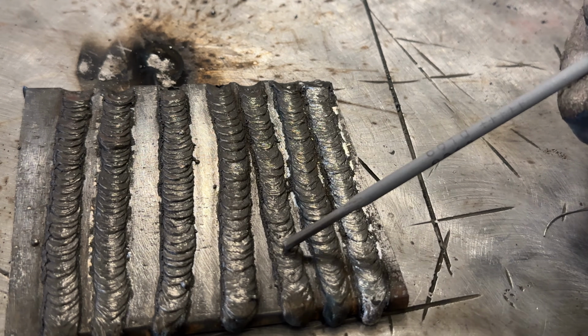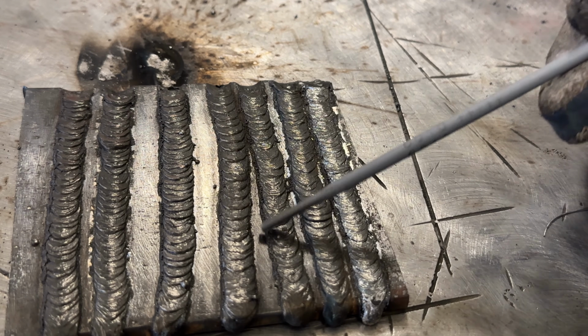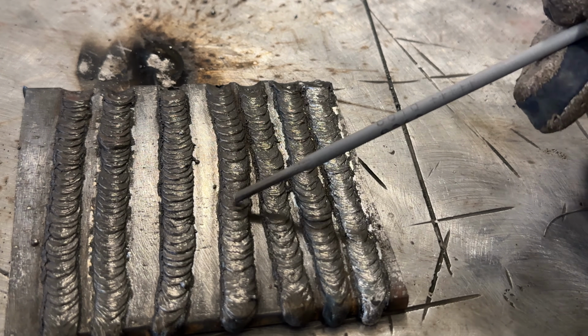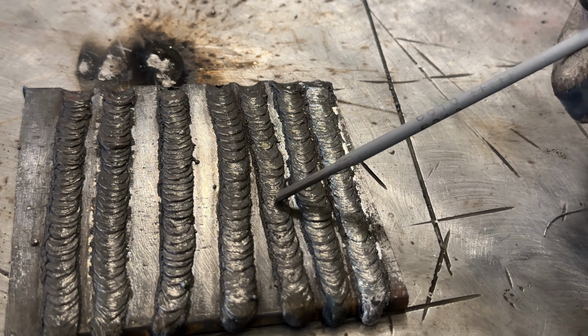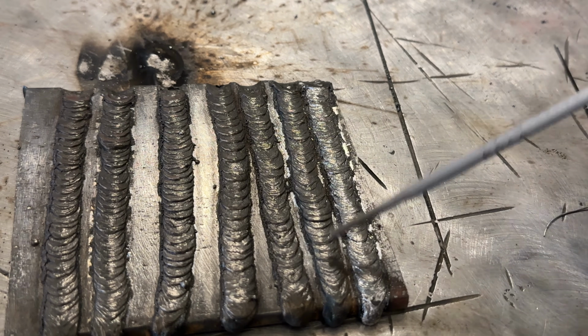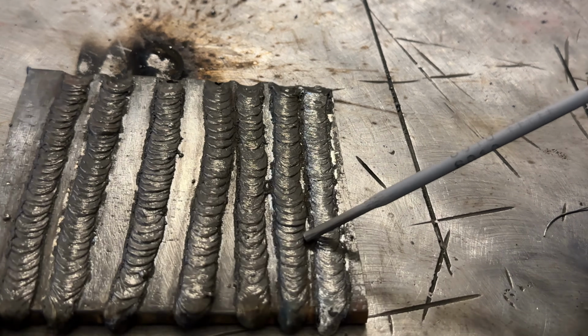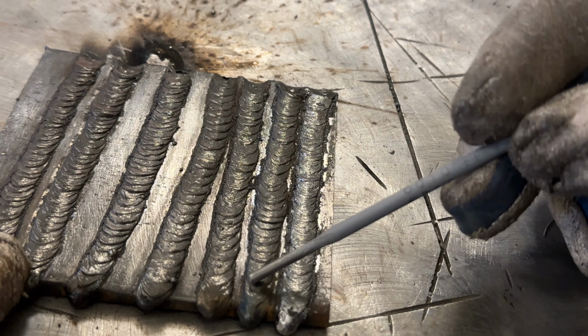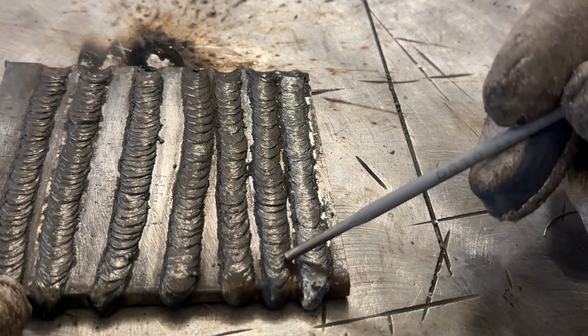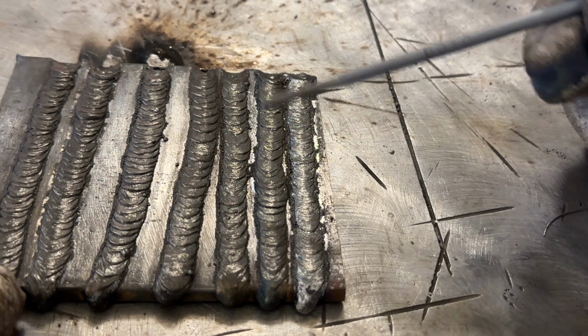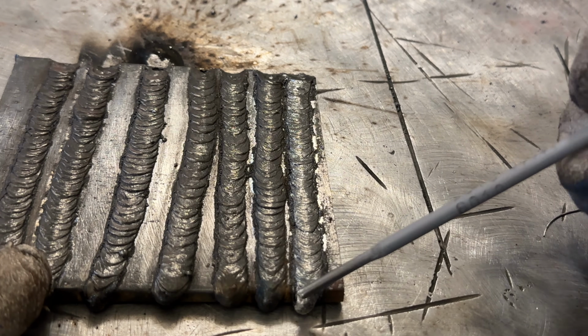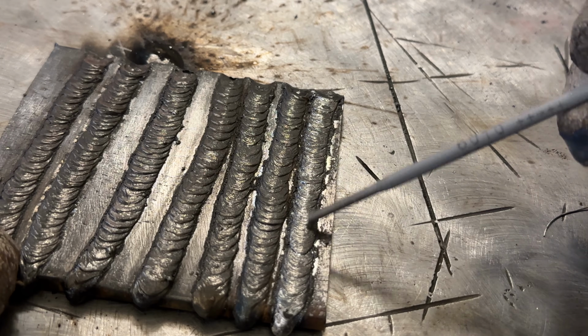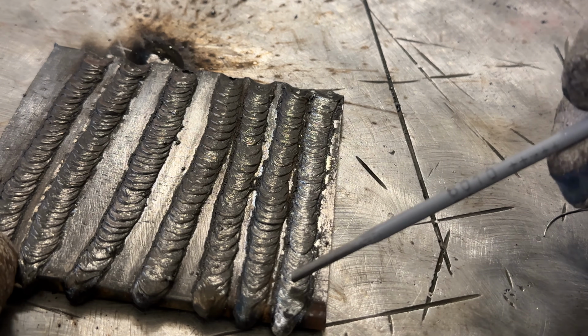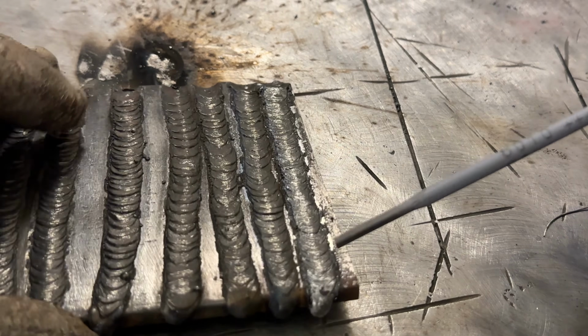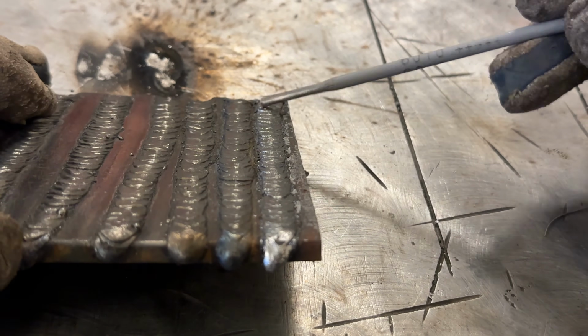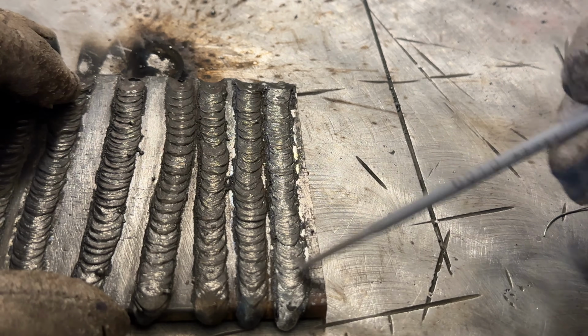So heat input will change. The higher your amperage or the hotter the plate is will change the distinct ripple pattern because it affects how fast the weld solidifies. Now, switching to 5P plus on a cool plate, it more or less looks even smoother than 5P on a hot plate. And then I cooled it off after this pass and ran this, and you can see being close to the edge, heat input was very high, and look how smooth that weld is overall. And that's because that puddle stayed liquid for far longer.